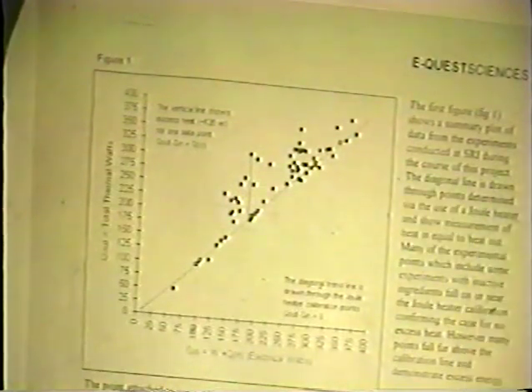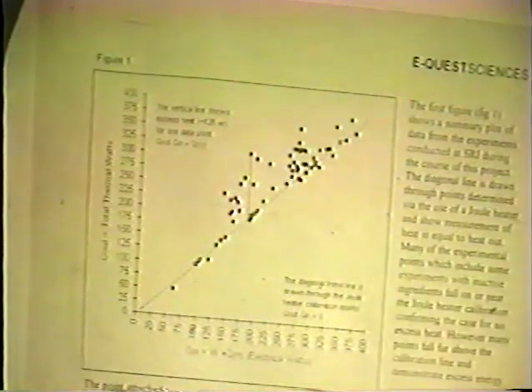Some of these are things like, there was quite a range of different palladium materials that had been received from different suppliers and with different treatments. Some were annealed and some weren't. Some samples had boron added to them because there was an idea that boron might be engaged in the reaction, it would improve it, and the boron experiments all fell. In fact, I think those are the 3 boron experiments. So we think that was fairly robust evidence that we can quite reliably produce excess heat. Not every time, but over the course of a week, we could probably do it 4 out of 5 days if we were asked to.